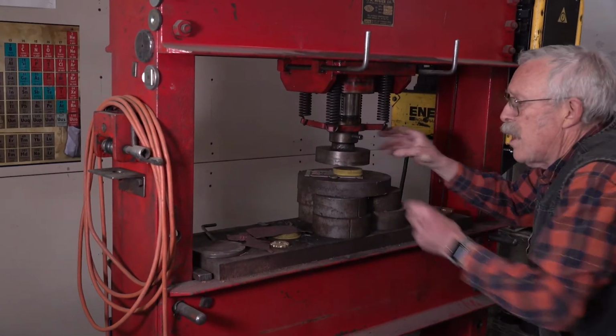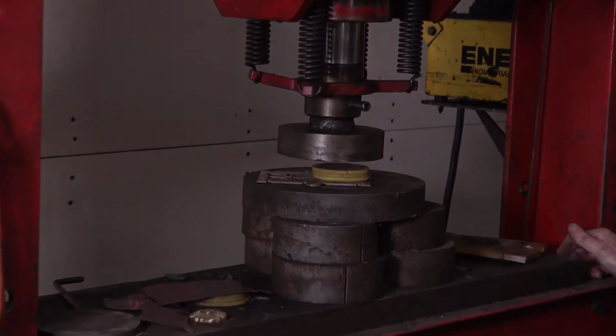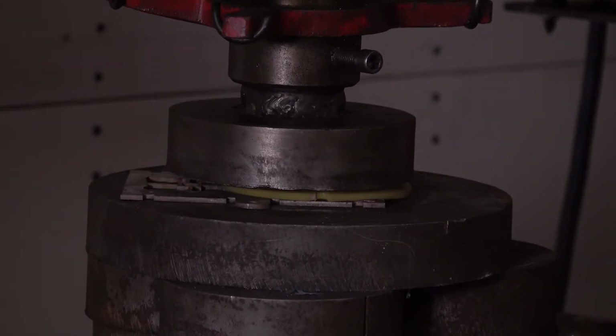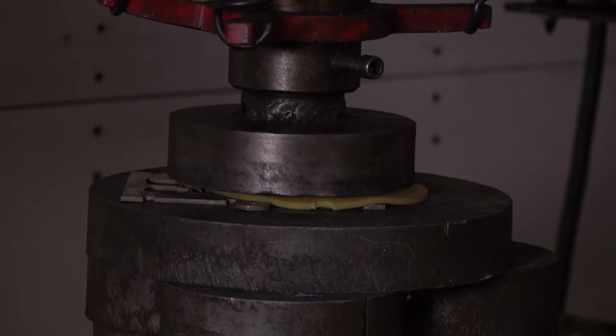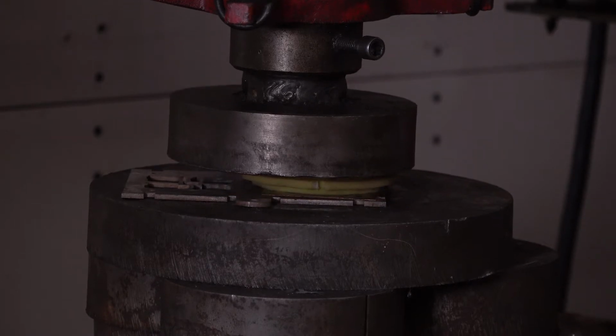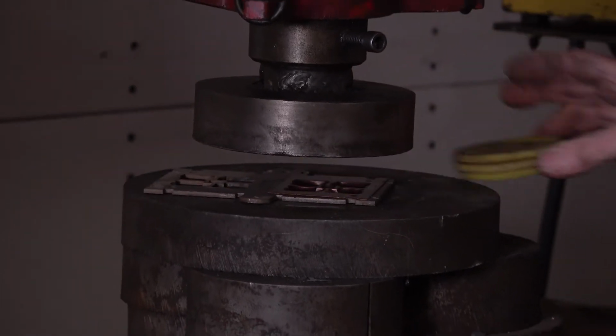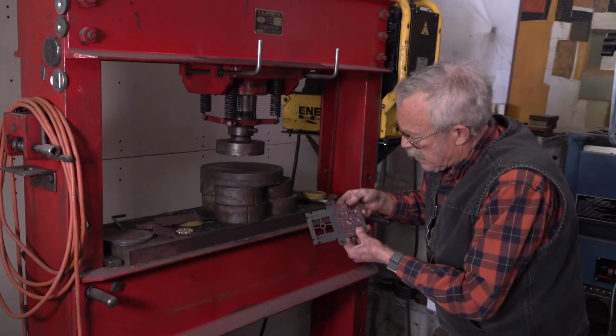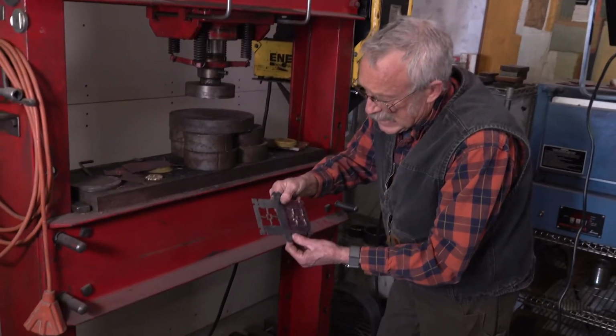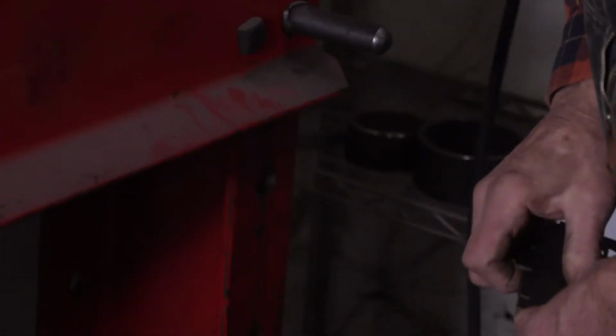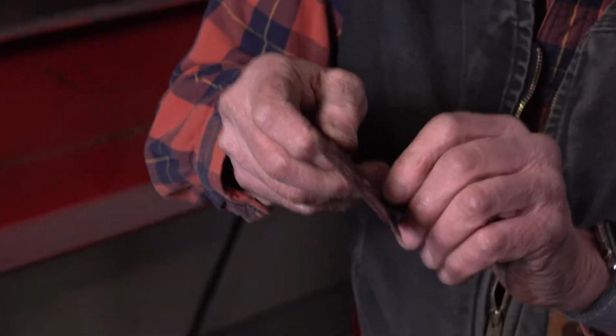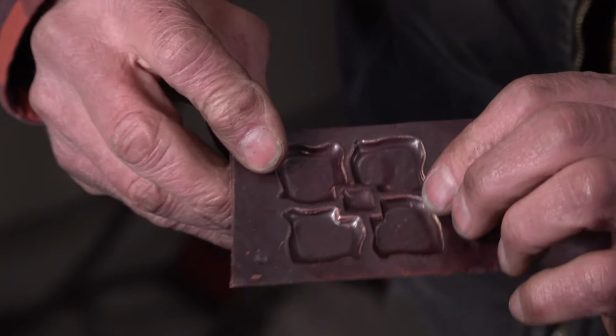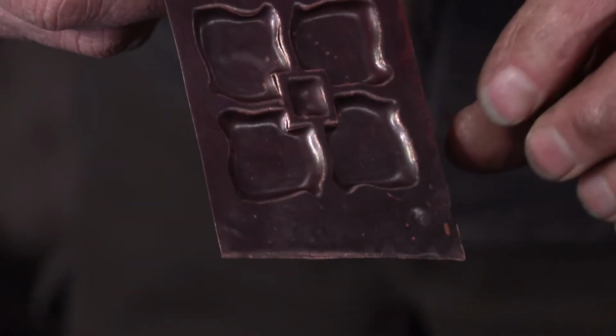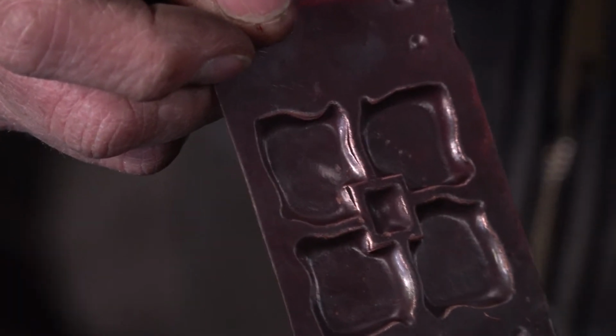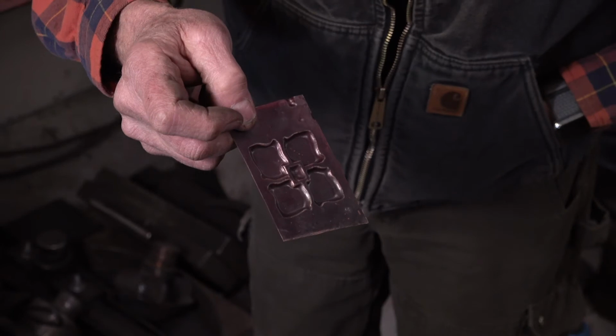And go to the next durometer, which is the real fine. And if you watch, it'll almost bubble out. And if you look at it, it looks pretty good, but when I pop it out, if you look at the centers and all around the edges, it's cut it. You can see it really well right there, because the metal just could not stretch, because it was work hardened just from that original push.